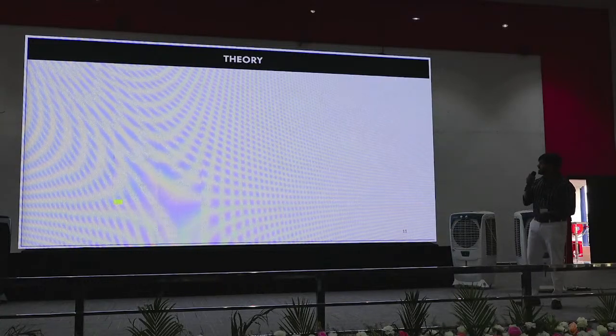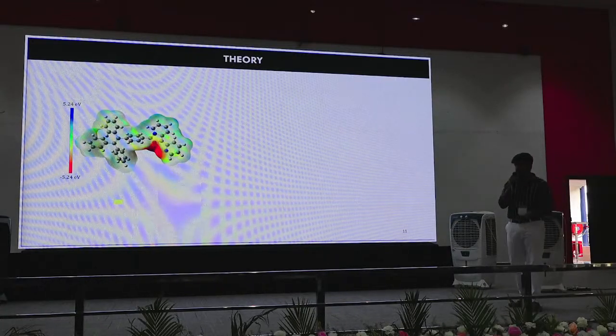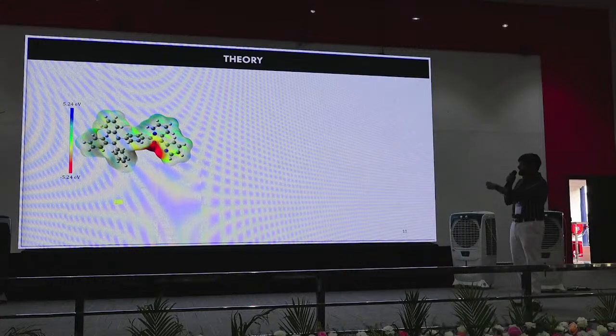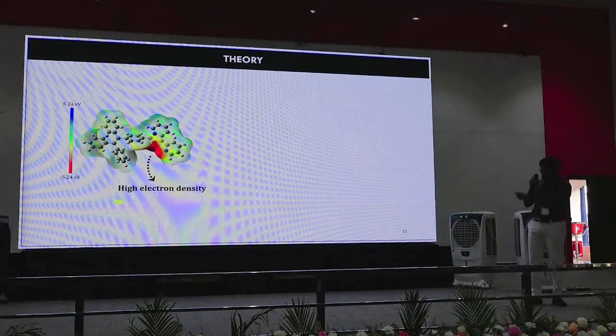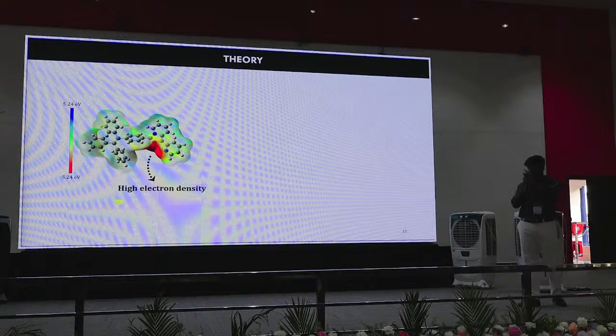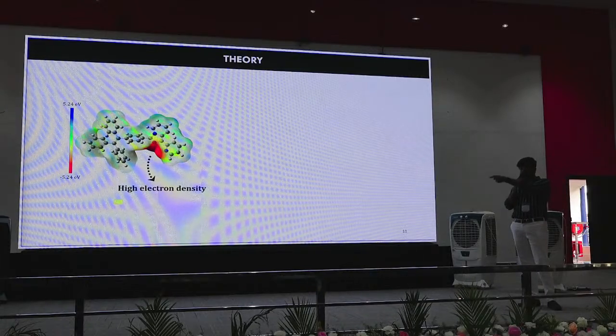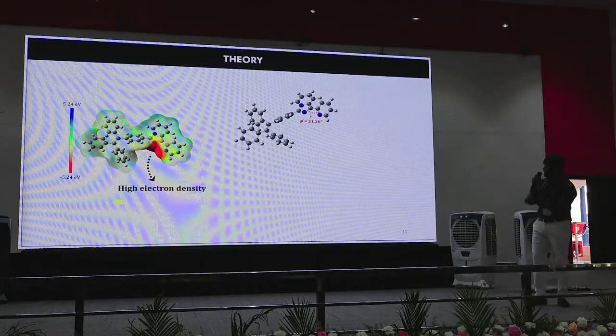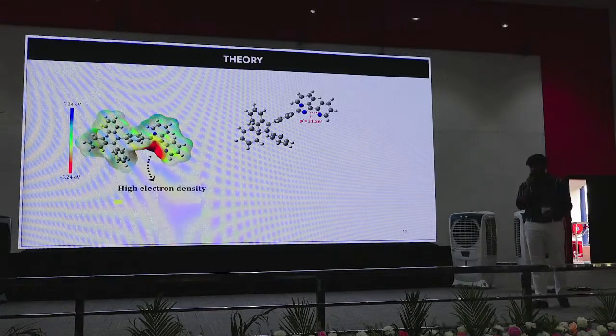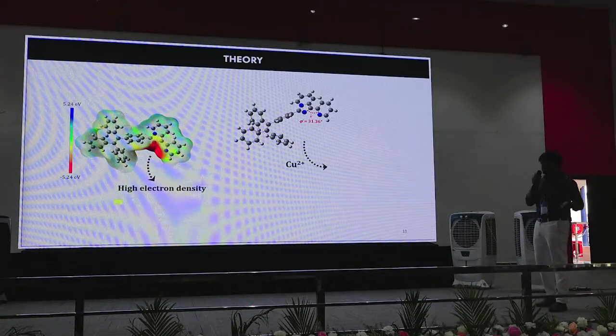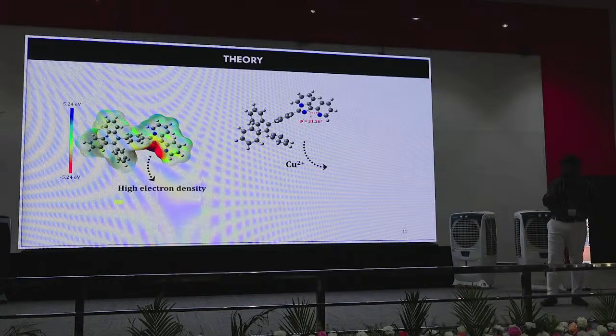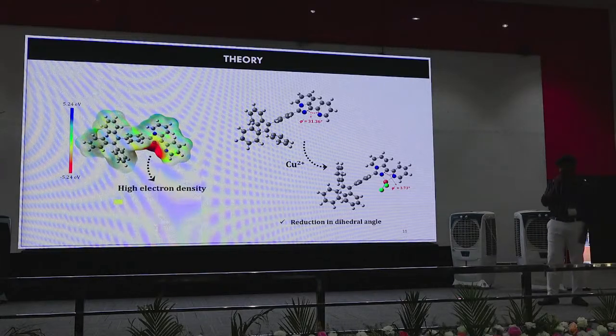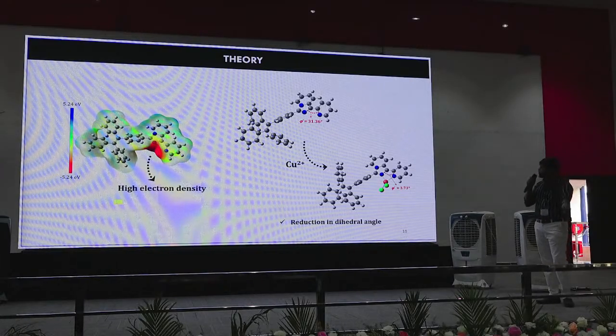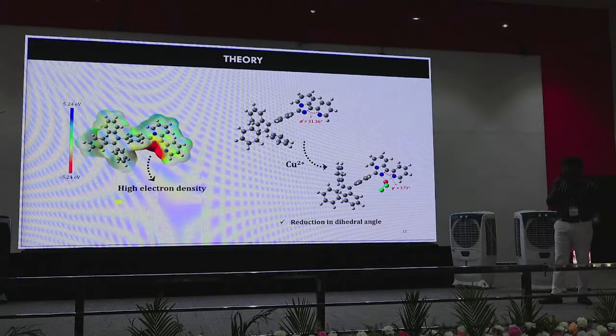And the theory behind it is we optimized the structure. As you can see, this is the MESP diagram. The high electron density is in the pyridine unit, that is, this can be the binding site for any metal ion. So here for copper, we optimized the structure. And when we introduced copper 2+ into it, the dihedral angle is reduced. It was reduced to 3 degrees from 31 degrees. So it is a huge change.